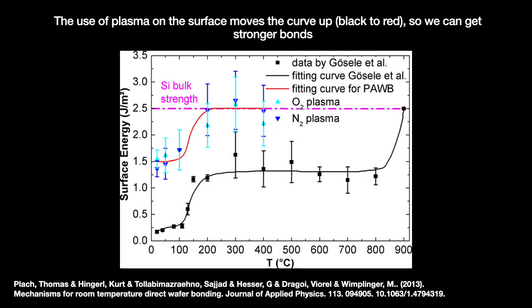So how do we get around this? We introduce plasma to the wafer surface before we bond them. The plasma does several things. First, it destroys organic contaminants on the wafer surface, cleaning it. And second, it lowers the activation energy of reactions like those forming strong silicon-to-silicon bonds. Thus, we can reduce the annealing temperature from 900 degrees to 400 degrees. Plasma-activated bonding is a developing industry, but the market has high potential considering its current value for items like backside power delivery networks, where we need to keep the devices from not melting like cheese.